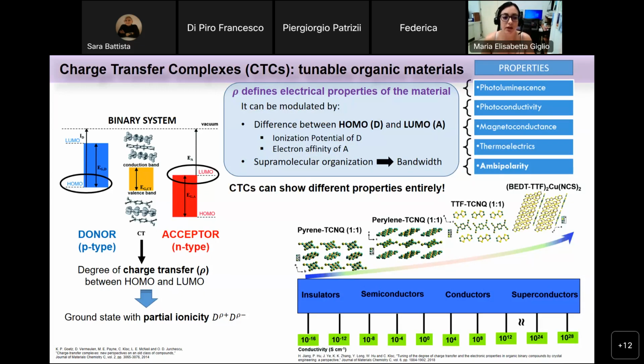One way is by tuning the difference between the HOMO of the donor and the LUMO of the acceptor. And another way also is by acting on the supramolecular organization of the final complex, which defines in the end the bandwidth of the final complex. So based on these, the charge transfer complexes can show very different properties entirely with respect to the parent compounds, which usually are unipolar semiconductors. So basically, a lot of properties have been detected so far in literature, and these properties can vary on a wide range from insulators to semiconductors to even conductors as superconductors.